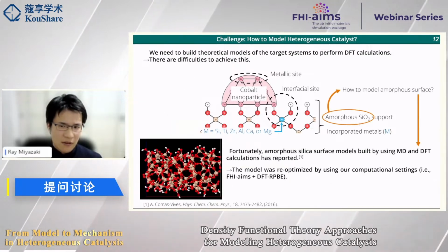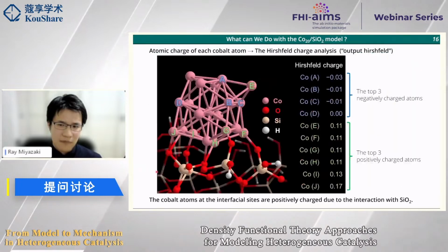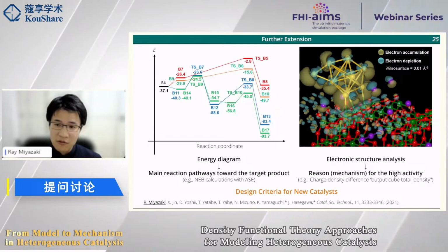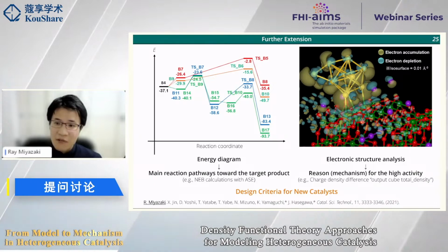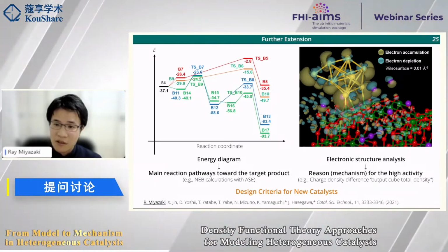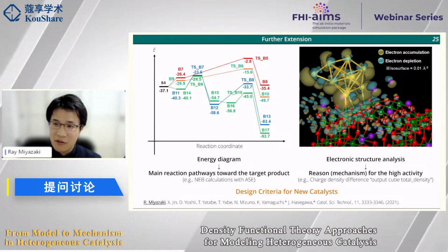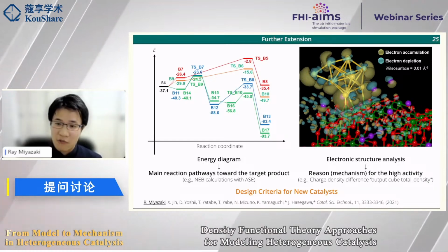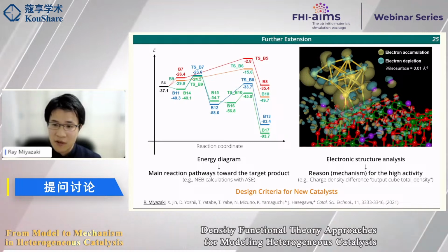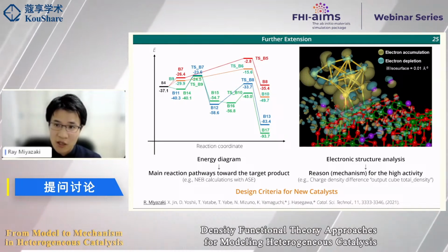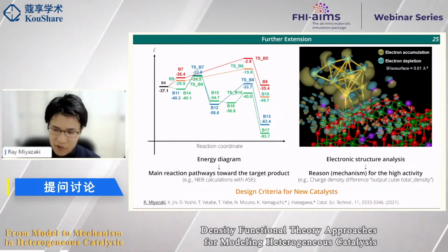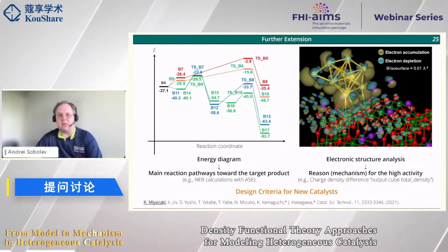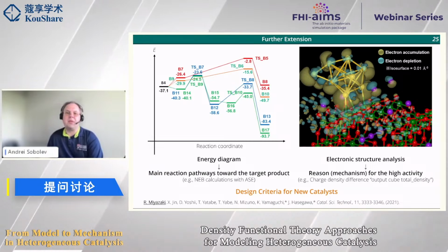Another point is, as I mentioned, in another study a gold nanocluster is supported on manganese oxide. For manganese oxide, we needed to think about this. I put an anti-ferromagnetic structure as the initial spin state for geometry optimization or SCF, and after the SCF, we can get the stable anti-ferromagnetic structure. So you are right, before performing the calculation, we need to investigate the most stable spin or magnetic structure of each material. Yes. Thanks a lot. Hope this answers the question.